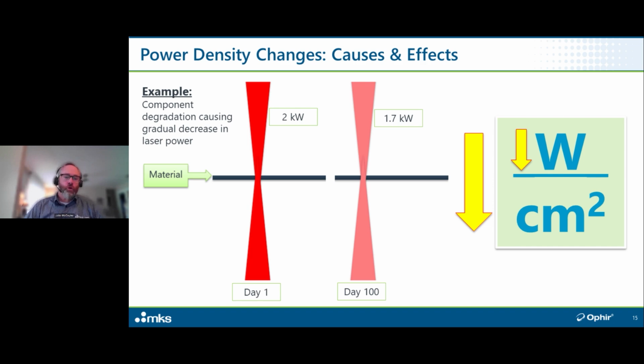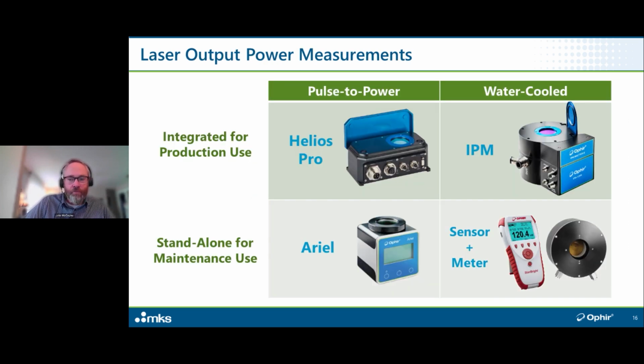So let's look at this crude cartoon here. Look at the example of component degradation causing gradual decrease in laser power. Day one, you've got a 2 kilowatt process. You've got the laser focusing down to the material. Everything is great. 100 days later, for whatever reason, you take a laser power reading and you've got 1.7 kilowatts. What's that doing to the power density? It's decreasing the amount of light that's being applied to the process, which results in an overall decrease of the power density and a loss of efficiency of that particular laser system.